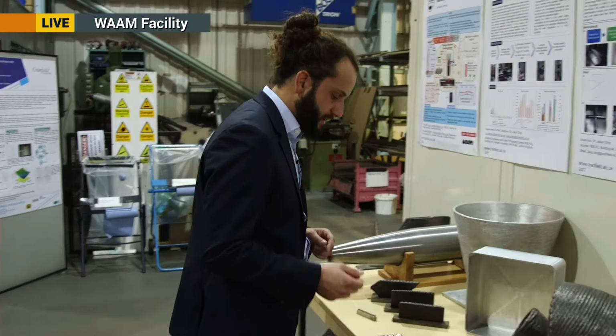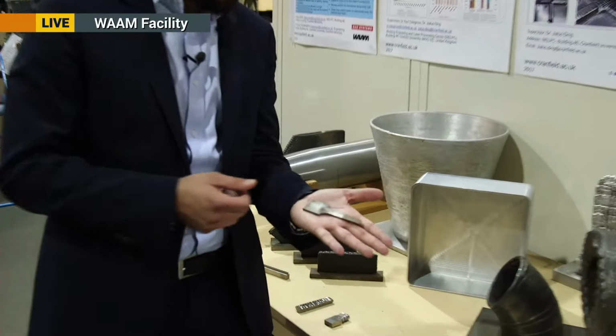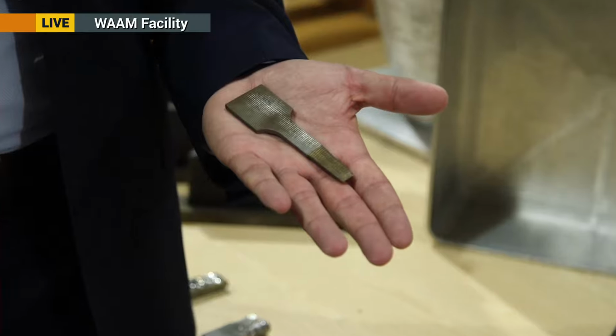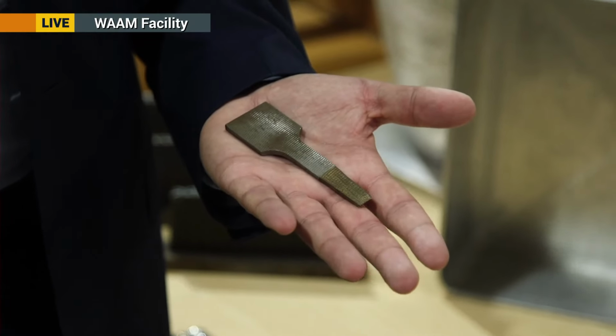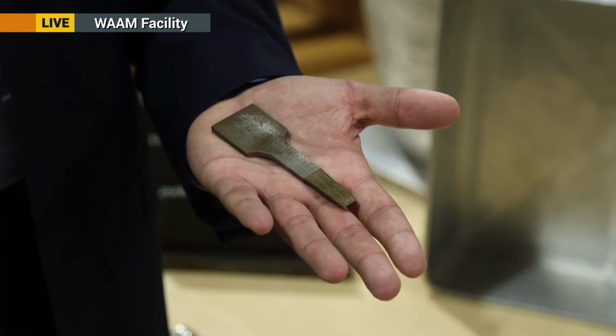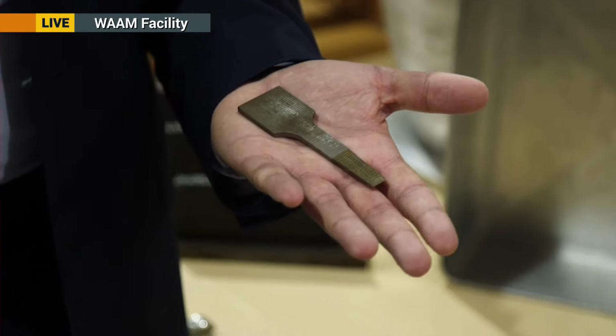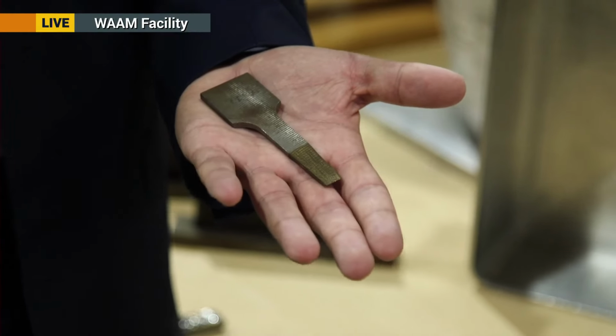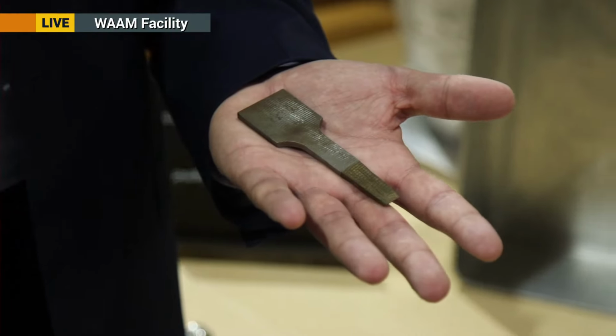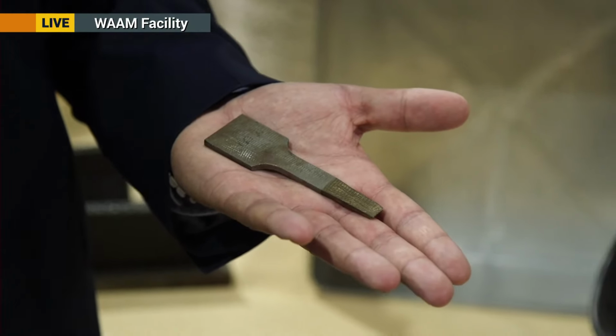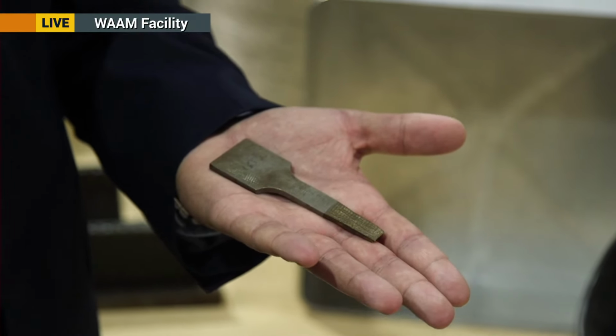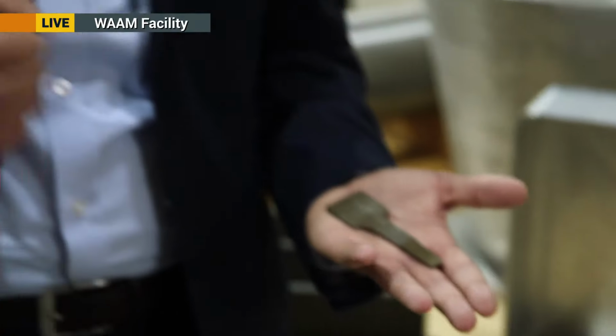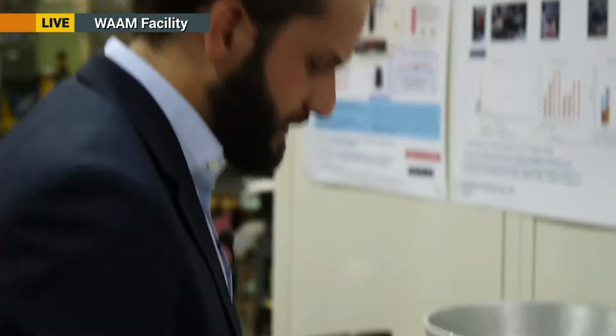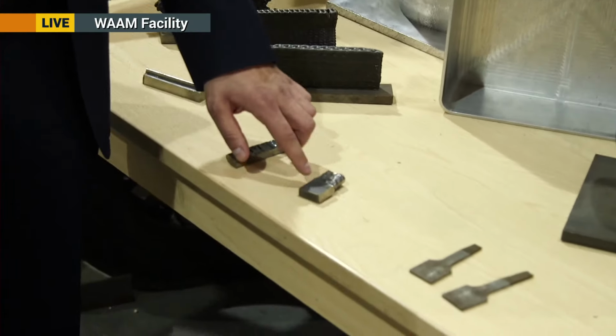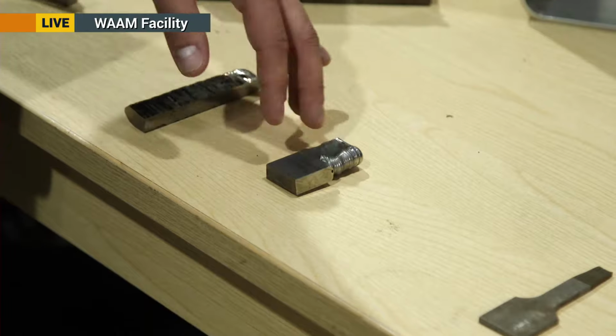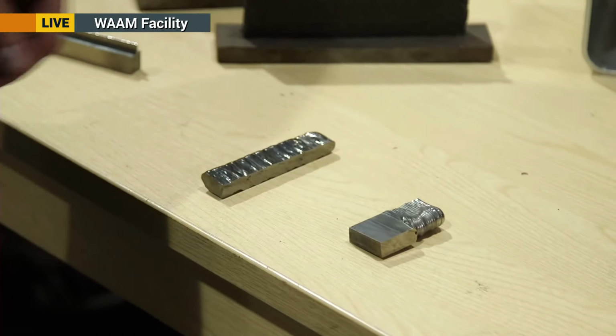As I was mentioning multi-materials, I'm just going to give you a quick example of a specimen made in a graded way from steel to a copper-based alloy. Provided that the two materials are metallurgically compatible and they expand and contract in a comparable way, it's actually quite straightforward for us to go from one to the other. We have already achieved it, for example, going from steel to Invar for carbon fiber reinforced polymers tooling. So in this case, not for the production of the actual part, but for indirect application, the tooling. But also for more exotic applications, for example, for the nuclear fusion industry, where we can go from moly to tungsten to tantalum and so on, which is something that you can see here.